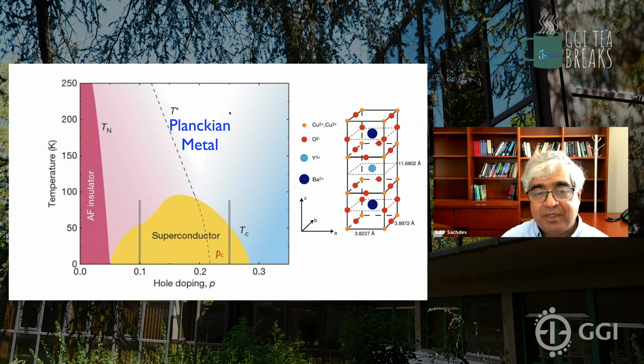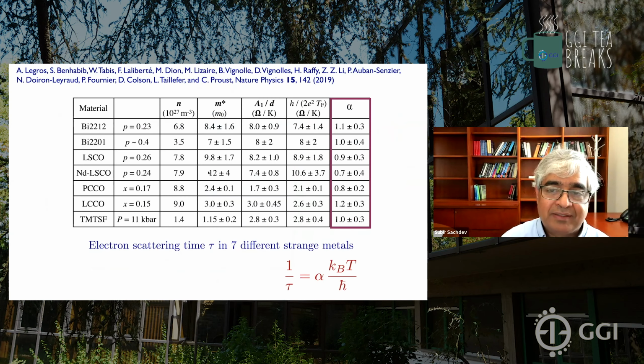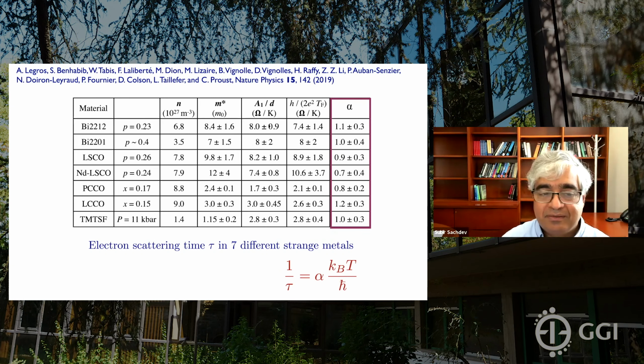So this is what people are calling the Planckian metal. One reason they call it the Planckian metal is that if you try to make some estimates of this scattering time, and I won't go into the details of how the experimentalists do it, this is one particular table from a fairly recent paper on many different materials in the same class. They measure the 1/tau, and they find to high accuracy it's actually a linear function of temperature, and this coefficient alpha is very close to 1.